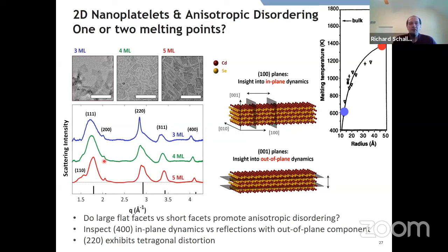And you might expect that because they're very, very thin. But in directions that have a component that is mainly looking along this direction, where you can put a lot of slices through this system, you get narrow diffraction peaks. And similarly up here at the 400, which is kind of advantageous to look at just because it's totally isolated. It's just looking at this one plane out here. These are also narrow in comparison to this guy, the 111.